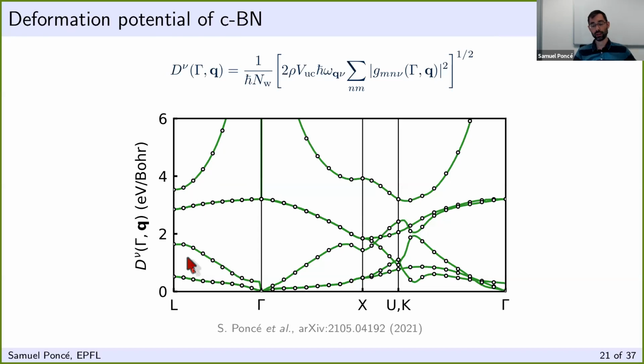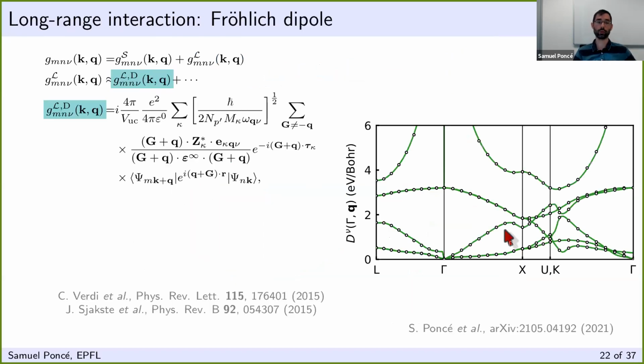So you can notice 2 things. We have this divergence, and then for this branch, for example, we have this discontinuity at the gamma point. In 2015, this was realized in the context of electron-phonon, but of course, this was realized much earlier in the context of the dynamical matrix and the phonon band structure. The strategy is to split the electron-phonon matrix element into a short range and a long range part. Now, the long range can be Taylor expanded in a multipole expansion, the first of which is dipole, then you have quadrupole, octupole, etc. The dipole has this analytic form where you can see that you have Q, G plus Q, the Born effective charge, and then you divide by Q, the dielectric function, and Q. So you have a 1 over Q divergence, shown by this LO mode going to infinity at gamma.